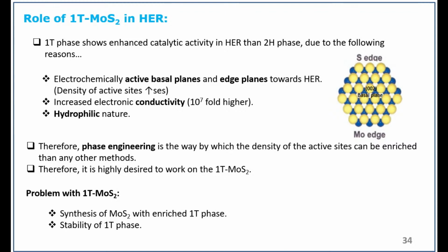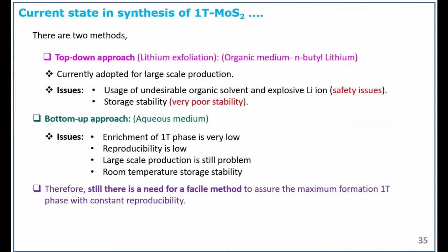But the problem is that synthesis of MoS2 with the enriched 1T phase is very limited, because we can go only 20% or 30% of 1T phase, and the remaining 70% will be the 2H phase. And whatever 1T phase is formed, within half an hour or 1 hour it will convert back to the 2H phase. So the two problems are there, and we need to avoid them. So how to do it?